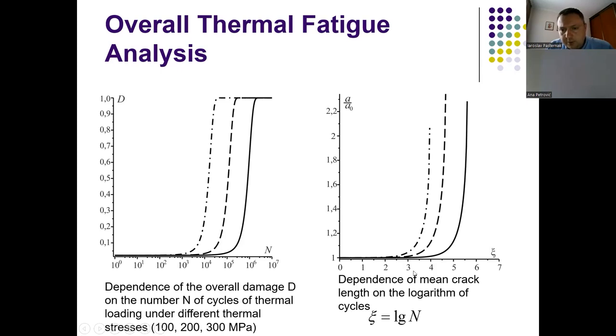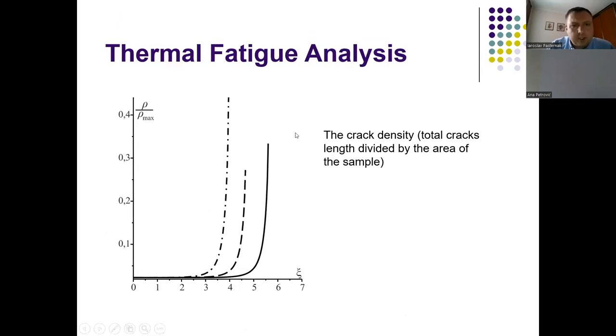When the loading is 100 megapascals, the crack length plays a big role when the number of cycles exceeds one hundred thousand cycles. Also we have determined the density of those cracks depending on the loading intensity and the number of cycles.